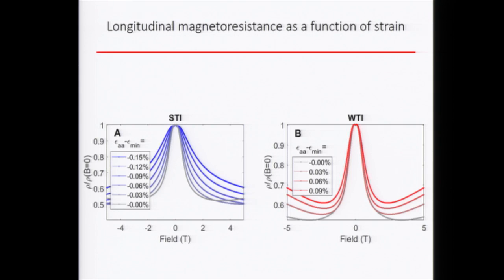The gray curve corresponds to when the resistance is sitting at the minimum, which is at the boundary, in the gapless state. The blue curve corresponds to going further into the strong topological insulator phase, and the red curve corresponds to going further into the weak topological insulator. So you can see that when you're straining away from the critical strain, you always get a weaker, more gradual decrease of magnetoresistance. This confirms that you really open a gap and suppress this chiral anomaly.